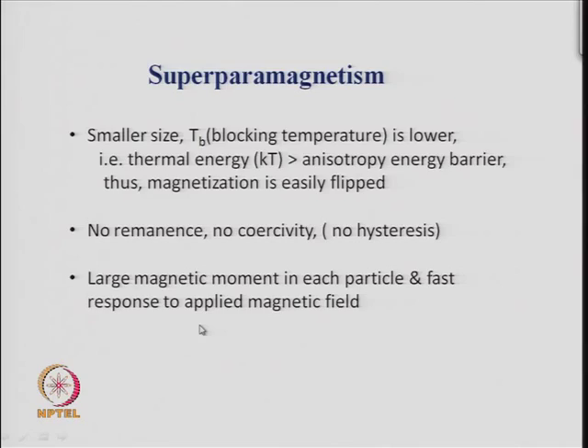That means, if you apply a field, the moment will be there, and if you remove the field, the moment will not be there. It will have a quick response to the applied magnetic field, and the magnitude of the magnetic moment will be larger in each particle, and that is why it is called super paramagnets. A normal paramagnet will have some magnetic moment, but when you have a particle with several of these moments aligned together to act as a single moment, then this single moment will have a much larger value, and that is why this property is called super paramagnetism.